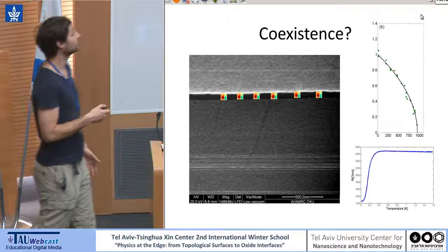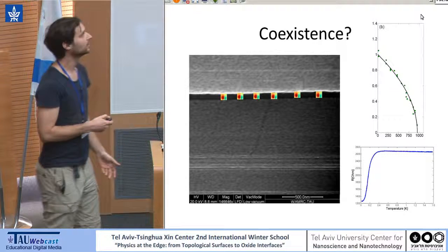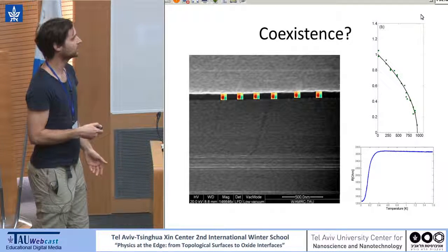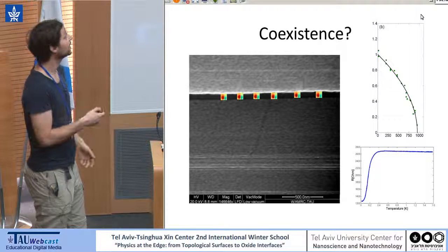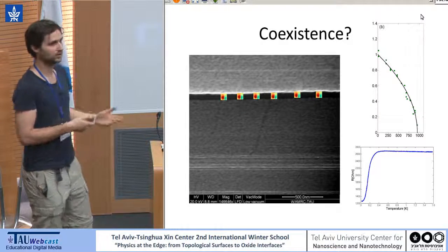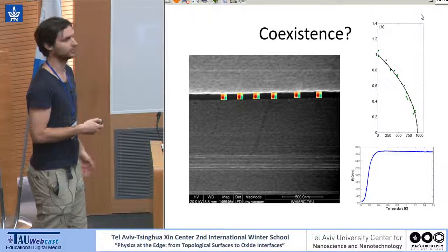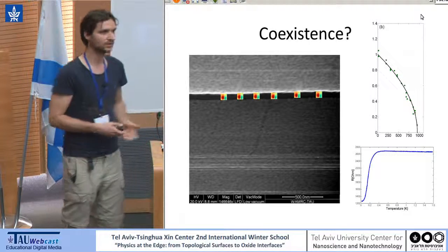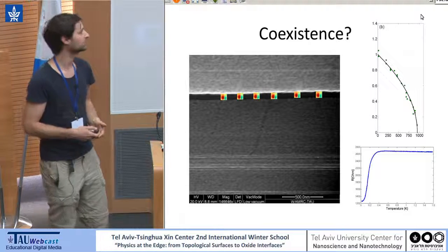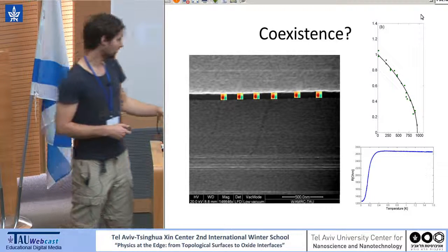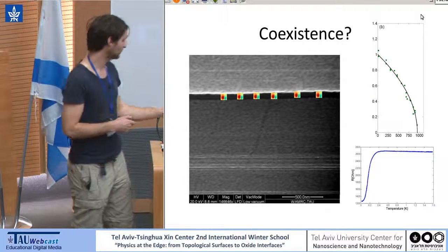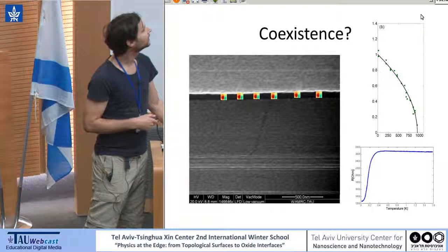So maybe if those dipoles aren't superconducting, this is the reason why we have this remnant resistance after the areas that don't have the dipoles in them undergo the superconducting transition. So this is why I'm saying even though it doesn't go to zero, I still call it a superconducting transition. With that, I would like to conclude on these wires and move on to the next type.